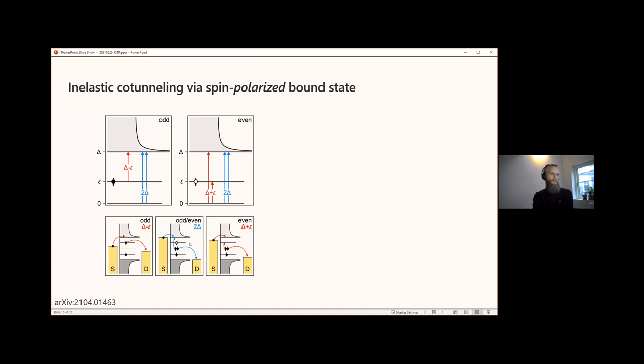This energy is provided by the voltage bias of the source and drain. Similarly, a Cooper pair can be split up, with both electrons put into the continuum, as shown here. The same can be done in the even occupancy, similar to the odd occupancy, yet the subgap state is not occupied. So we can break up a Cooper pair, put one electron into the subgap state and the other into the continuum, and this costs less energy than two delta if the subgap state is present.